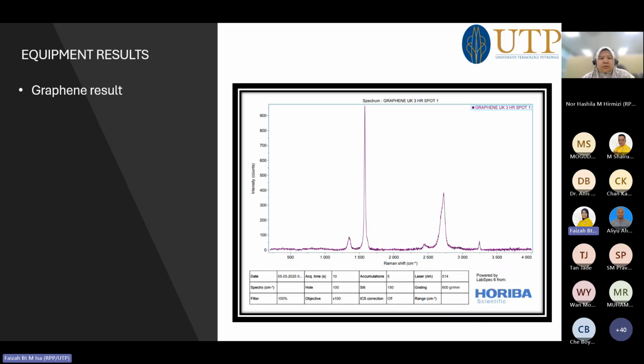So they can know the key Raman peaks for graphene identification, the graphene peaks. If you see a sharp G band at 1580 centimeter, a clear D band at 1350 centimeter, and a 2D band at 2680 centimeter. So this is the graph, and you can see we use a filter 100%, objective 100x, and grating 600 laser. So this is the result the software gives.